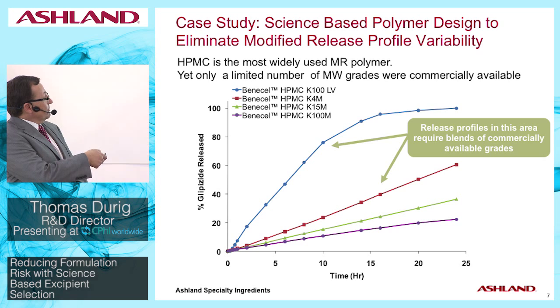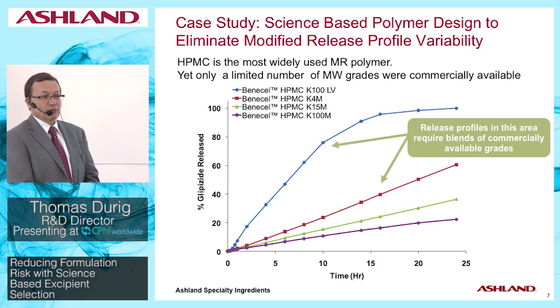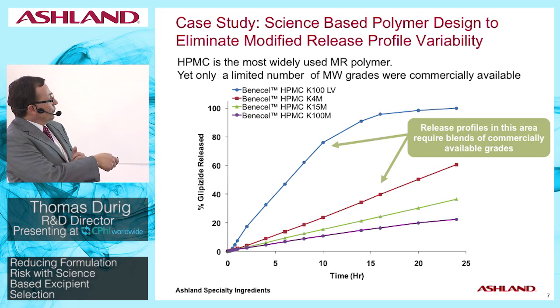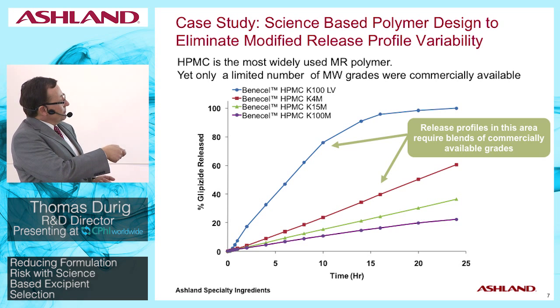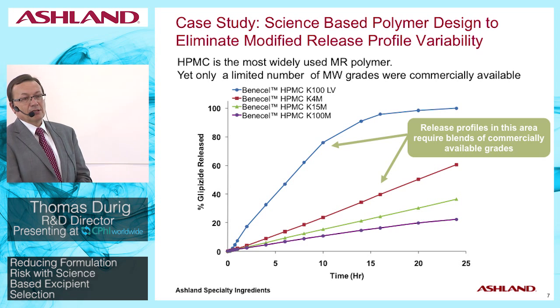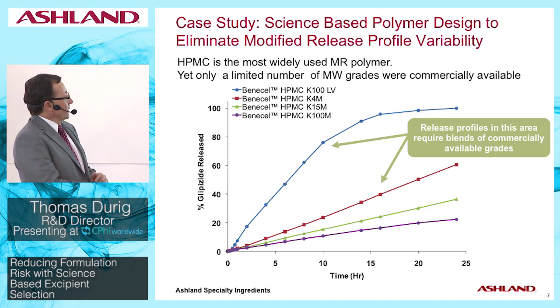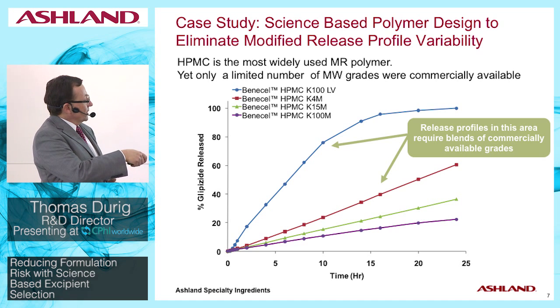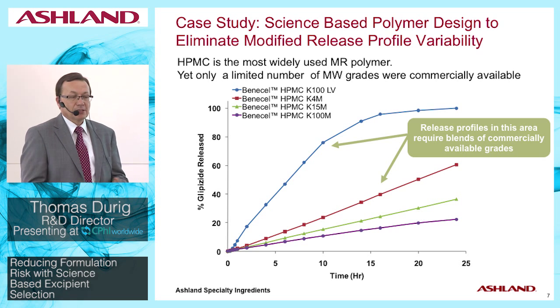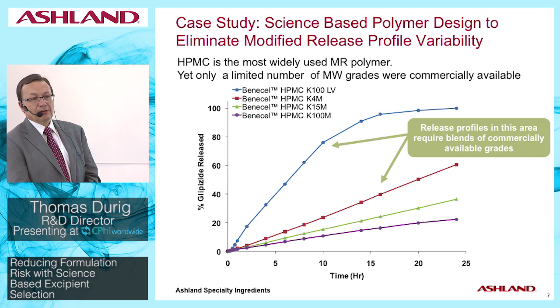And this immediately highlights a problem. Here we have an example of glipizide, which is a moderately soluble drug, incorporating 25% of all these different polymer grades that were commercially available at the time. You can immediately see that there's a lot of white space here in the 24-hour factor space. And the 24-hour duration for drug release is the physiologically relevant one in the case of oral drug delivery. And as you can see here, if, for instance, a formulator needed to achieve a release rate that fell somewhere in between here in this white space, they really wouldn't have an existing product that they could choose.